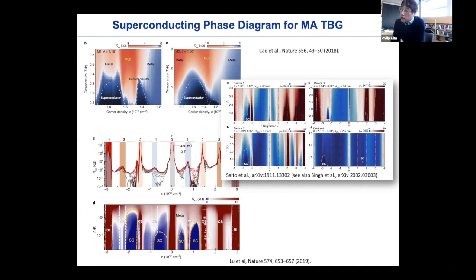Now, the trouble here is that it seems like every sample shows a slightly different type of phase diagram. Of course, as the sample quality progresses we see more of the details, but also a slightly different angle shows rather different physics, where the angle may not necessarily be under the exact control of the experimentalists, right? We often target some angle and end up with a slightly different angle, which we then study. So one of the jokes among experimentalists is that every sample makes one separate phenomenon and a separate paper out of it.